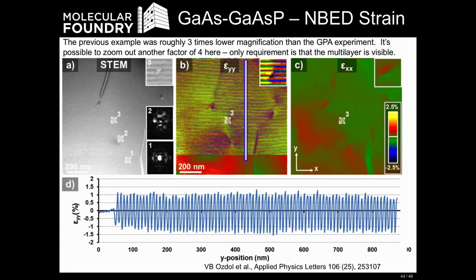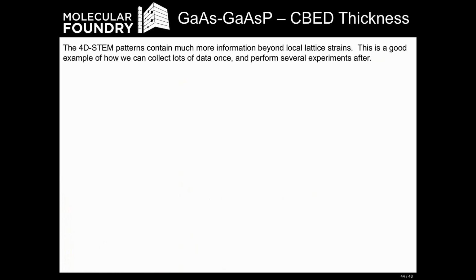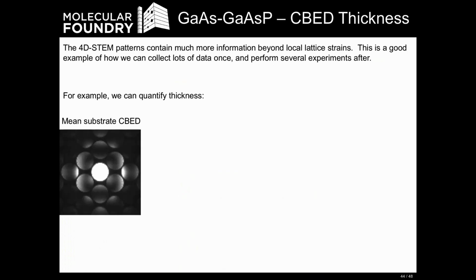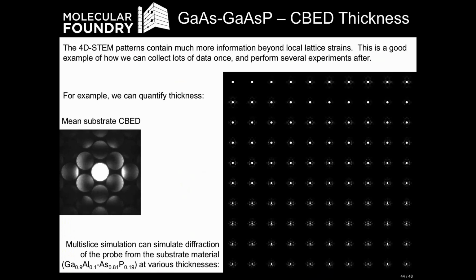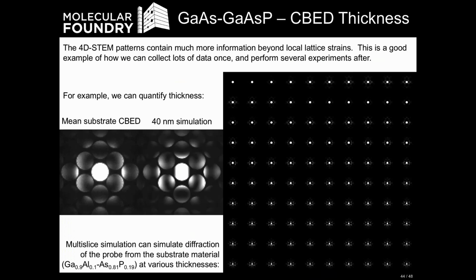One last thing I'm going to show from this too. We can once again do multiple experiments. We have a full diffraction pattern under every probe position. Here we're showing strain, but why not also, for example, measure the thickness? So if we look at the mean CBED image for the substrate here, and I want to figure out how thick the substrate is, on the right-hand side, I'm showing a calculated library of CBED patterns. And if I fit the mean absolute difference between each one of these patterns and our experimental CBED pattern, I can come up with the minimum error plot here.